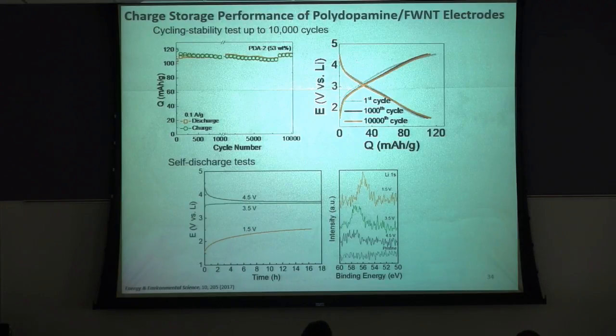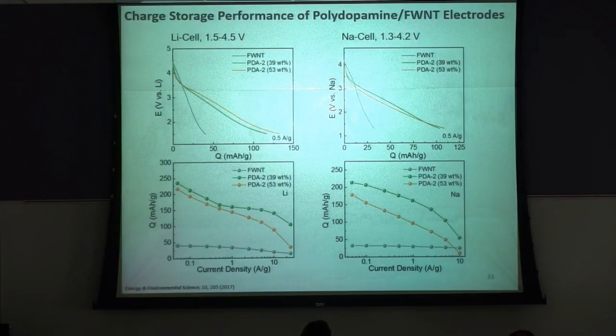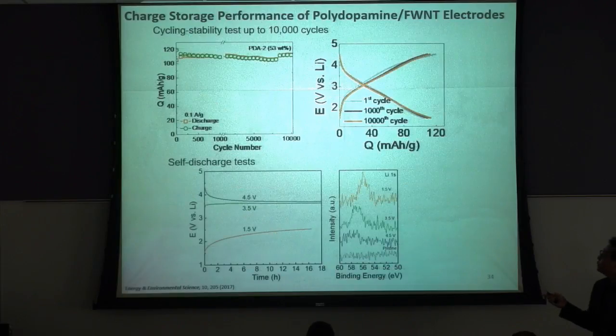So one of the weaknesses of this polydopamine composite film is the low capacity based on the total electrode mass, right? So only 120 or 130. If we compare previous graphene, that was around 150, right? So then to overcome this kind of low capacity issue, we use a different polydopamine functionalization process. So here, we mixed dopamine with the graphene oxide dispersion together first. Then we apply the hydrothermal reaction. During the hydrothermal reaction, polydopamine is coated on the surface of this self-assembled graphene oxide.